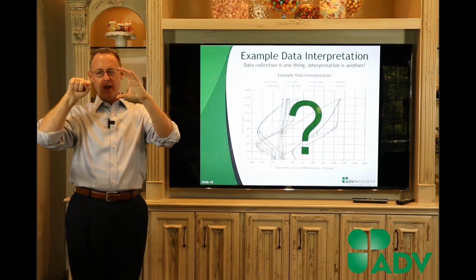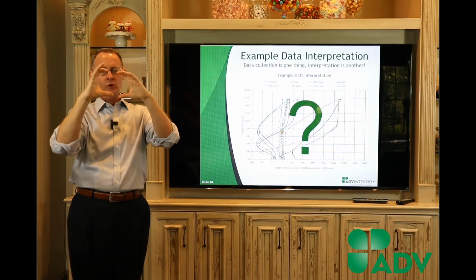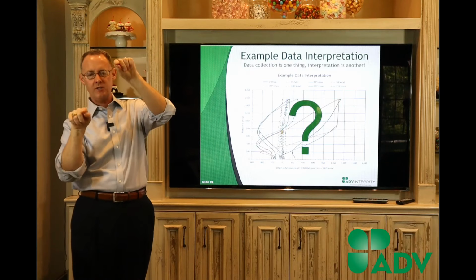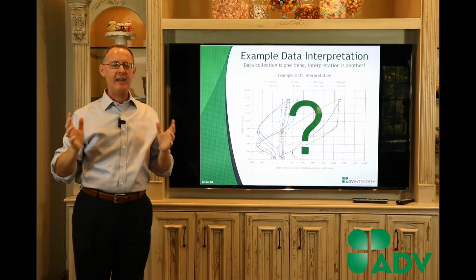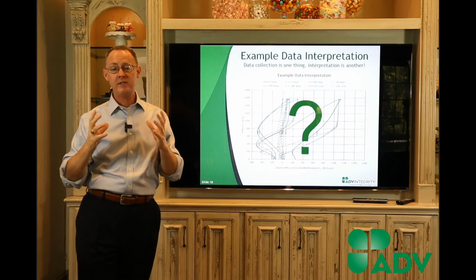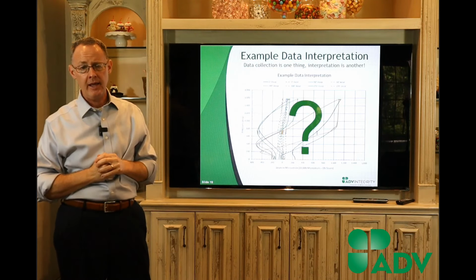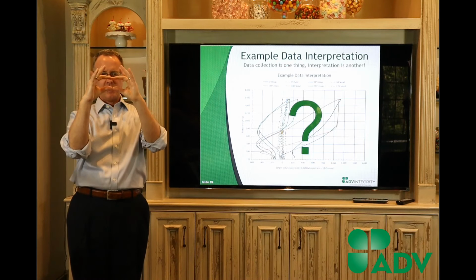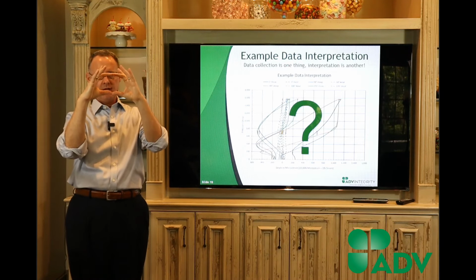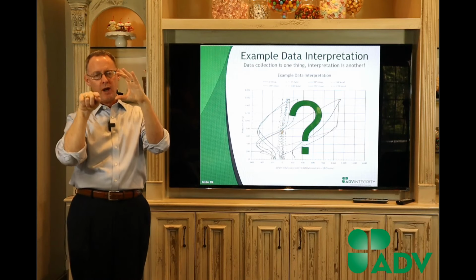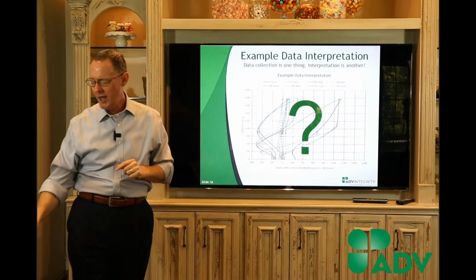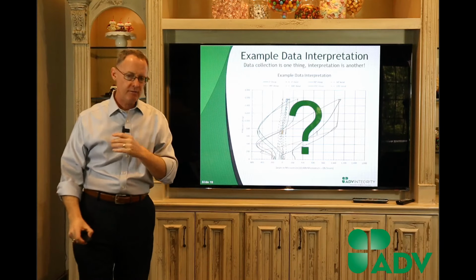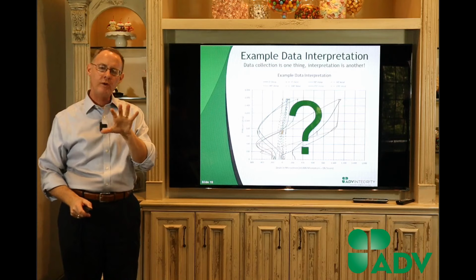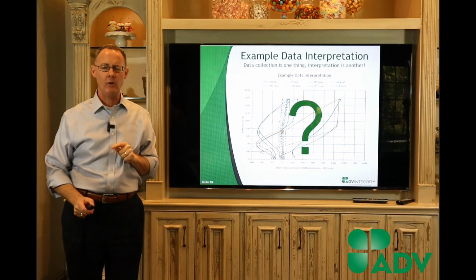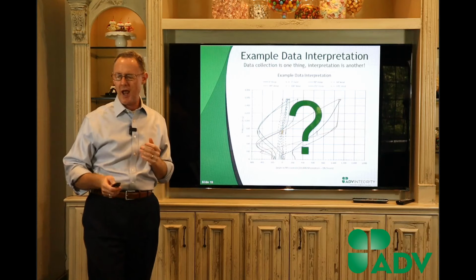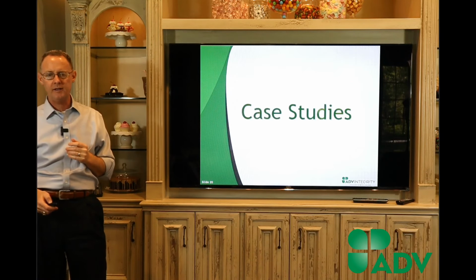But we had gauges all the way around, and we were getting some really weird readings. Like, 90 degrees of strain was different here. And if you're doing anything with large diameter pipe, it always has some level of ovality in it. And so what happens when you've got ovality, when you're pressurizing, and I'm exaggerating a little bit here with my hands, but you create an ellipse, and as you pressurize it, the strain changes around the circumference of the pipe. So we spent a couple of hours and then eventually a couple of weeks processing through it to the point where we felt like we understood what was going on. So it's not just collecting data. Sometimes there's a real challenge in knowing what to do with the data once you collect it.